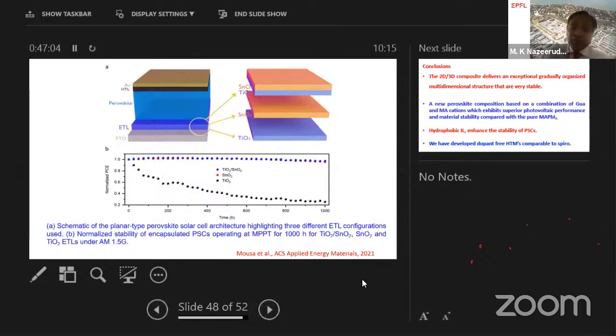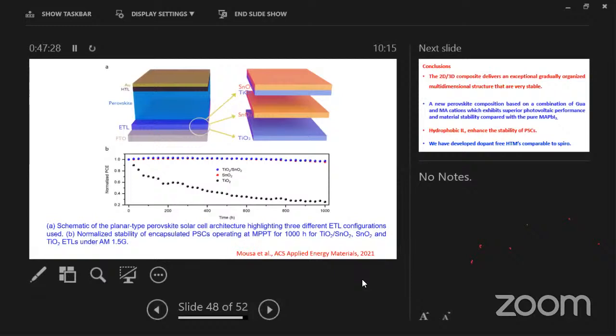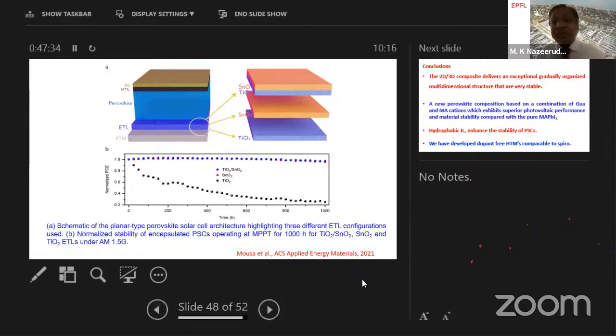And at the same time, we can also manipulate, having TiO2 followed by tin oxide, that's a blue line. So that's a mixed oxide layer. You can see more details of this work in Applied Energy Materials. Using this type of electron transport material, we reached over 21% power conversion efficiency. So I have demonstrated interface engineering. Can you just take us to the next slide, please?